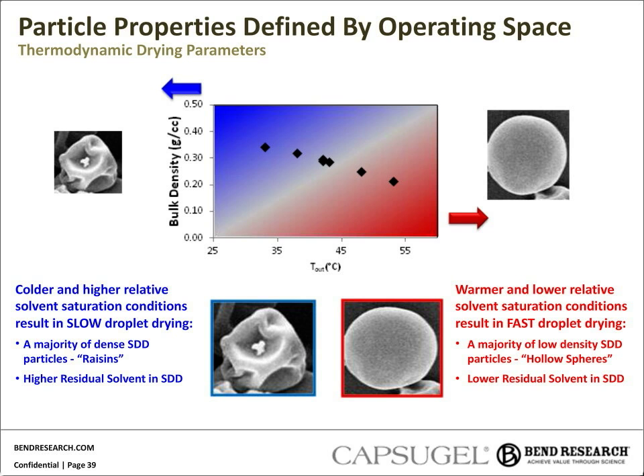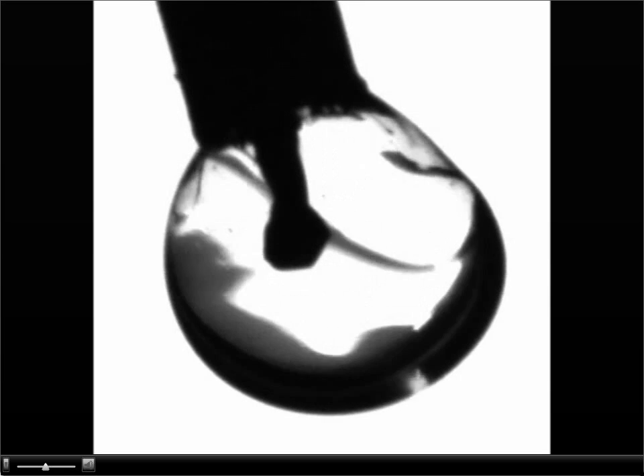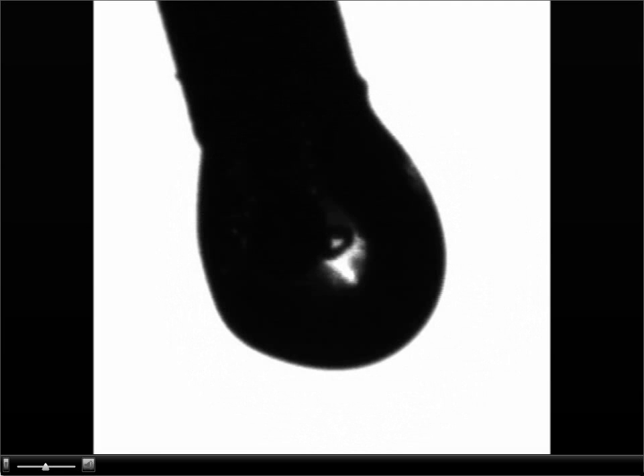If the drying rate is fast or the spray drying parameters are hot and dry, this skin is more rigid and the solvent diffusion through the solidified skin is slow. The partial pressure of the solvent can build up inside that droplet skin, resulting in an SDD with a more balloon-like morphology that has lower density and higher compressibility. So we'll show some videos of droplets suspended on a thermocouple and subjected to first cold, wet drying conditions, demonstrating the raisin morphology, and second, the hot, dry spray drying conditions, illustrating the faster droplet drying and the balloon-like morphology.